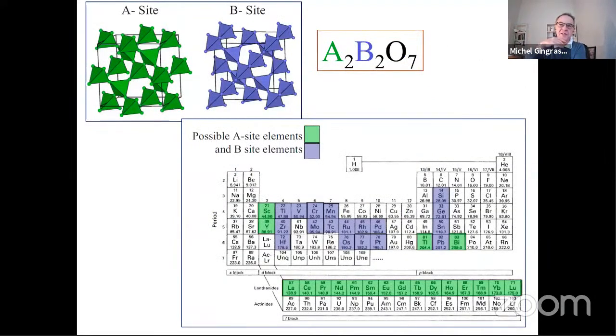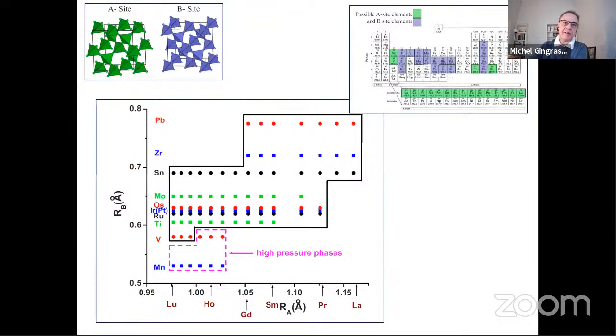So there's a large variety. There are literally thousands of these A2B2O7 pyrochlores, and they have to satisfy some stability rules. It's not like you can have an arbitrary combination of the trivalent A site and B site. And this chart here illustrates a bit what's possible. So for example, if you look at the B site, what I referred to as the M site earlier, I apologize for the change of notation. If you have the transition metal site occupied by tin, Sn here, then for the rare earth sites, all the lanthanides are possible from lutetium all the way to lanthanum. So the heavy rare earths to the light rare earths.